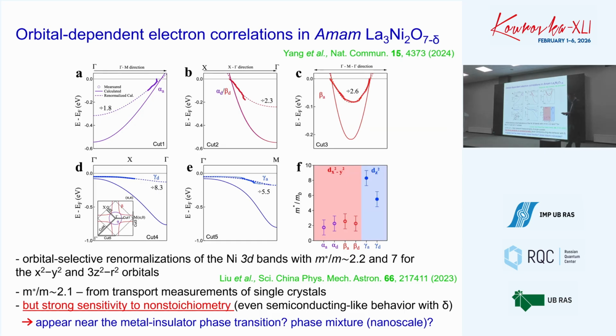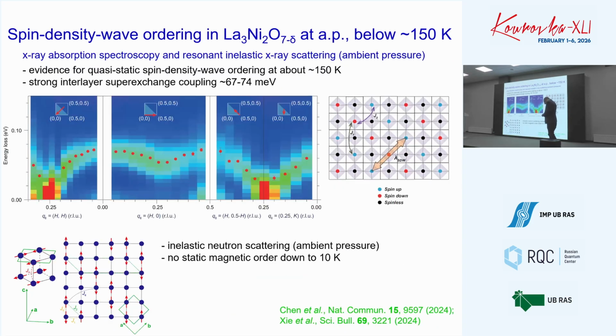Of course, all this data is very sensitive to non-stoichiometry, and in some cases it results in a shift of the critical pressure, etc. Even people don't manage to reproduce in some samples this zero resistivity state. We do see the presence of some extra phases like nickel oxide, which modifies this result.